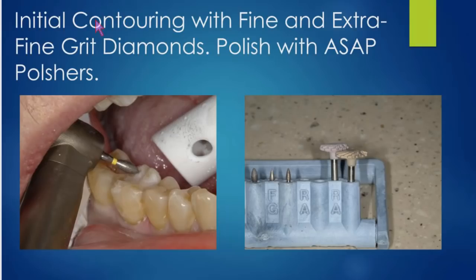In this one bulk filled class 2 composite, if you'll remember, this patient had no proximal contact on the mesial, and there was an area of micro leakage on the occlusal surface. So we went through our selective etch procedure. We used our G Premio bond, and now we've placed our material in full, in bulk, and now we're going to come in with our finishing.